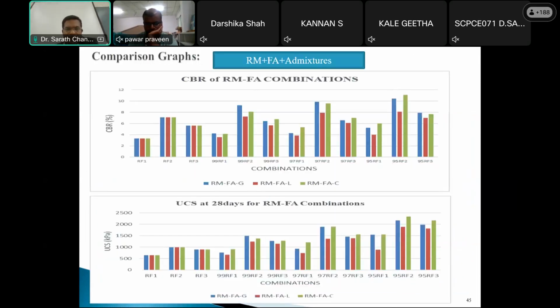And here are some comparisons I made with various combinations. Basically, I focused on CBR and UCS. CBR and UCS at 28 days and CBR at 4 days for red mud fly ash combinations are projected here. The blue line indicates red mud, fly ash, and gypsum. The red and brown lines indicate red mud fly ash with lime. The green line indicates red mud fly ash and cement. Now, almost all the cement combinations have better strength. Only with 99 RF2, gypsum has better strength, because in some places even gypsum has shown better results compared to the lime.